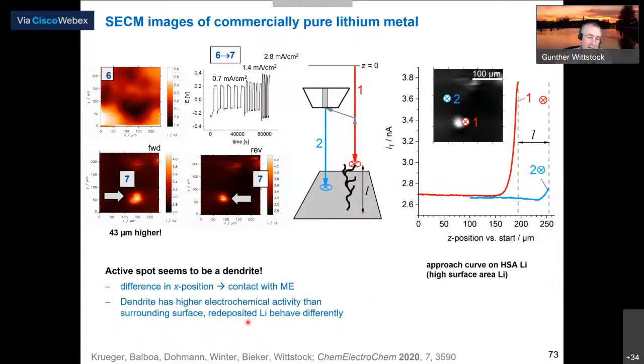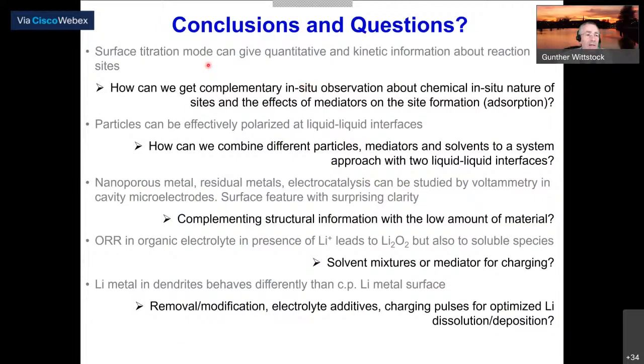So that means this high surface area lithium, which is deposited in such procedures, is not only rising up from the original surface, but it also has a higher reactivity, or the solid electrolyte interface formed on such structures does not prevent the electron transfer reaction as well as the layer on the normal lithium electrode. Okay, so as conclusion, the surface titration mode, which I introduced initially, can give quantitative and kinetic information about reaction sites.